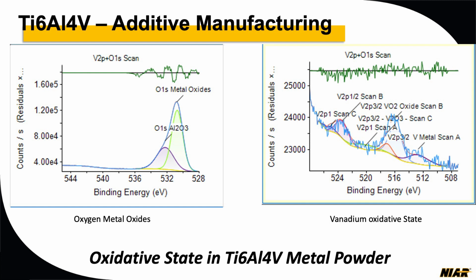So this is another one for metal oxide and aluminum oxide, showing the percentages. And vanadium has almost 3 to 4 different states that we have found. Again, the vanadium percentage was very low. That's why we have a little bit noisy data, but it was definitely present throughout the study.